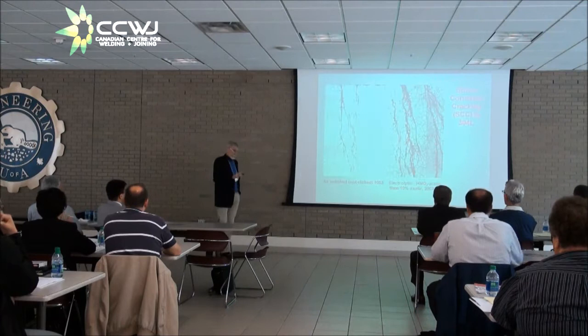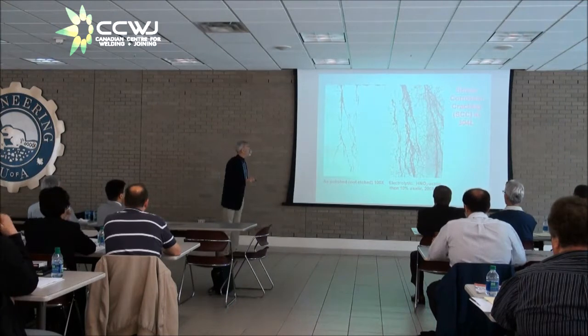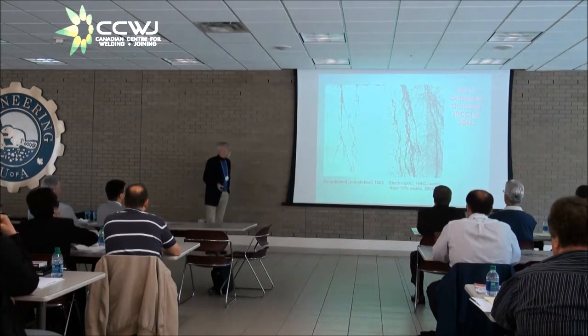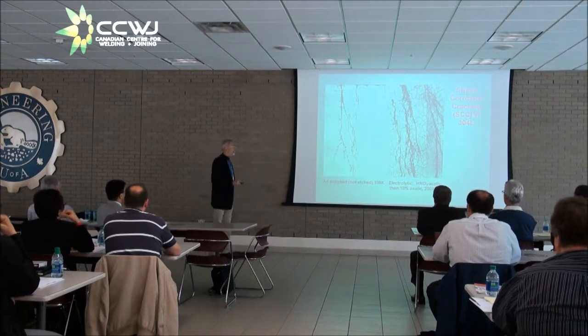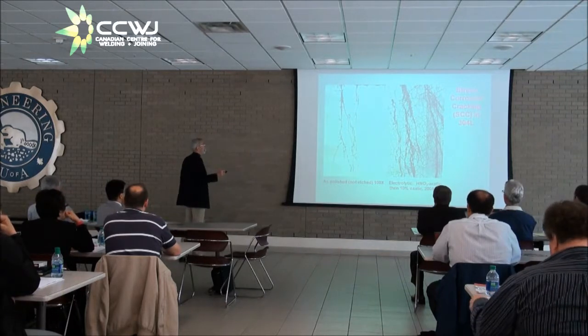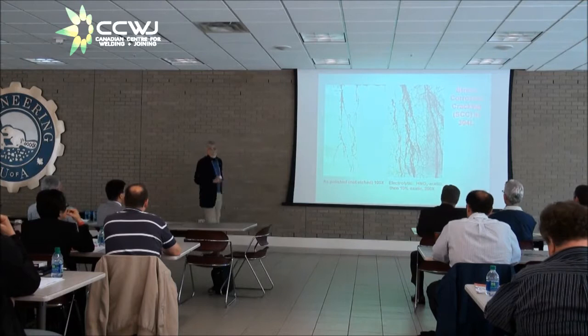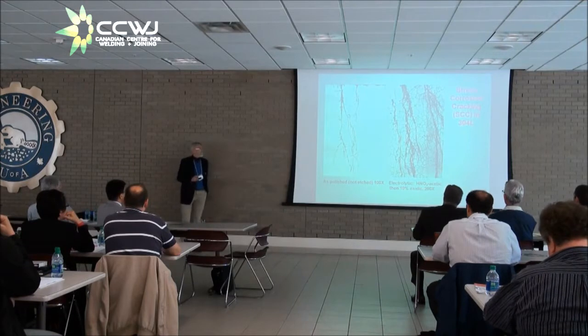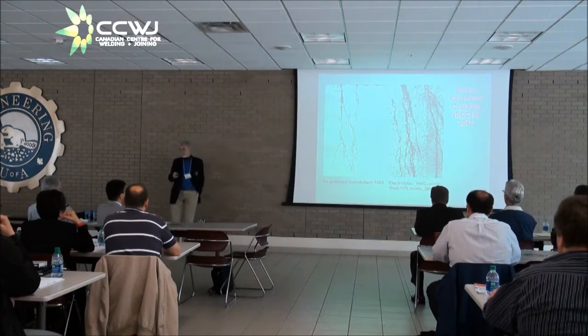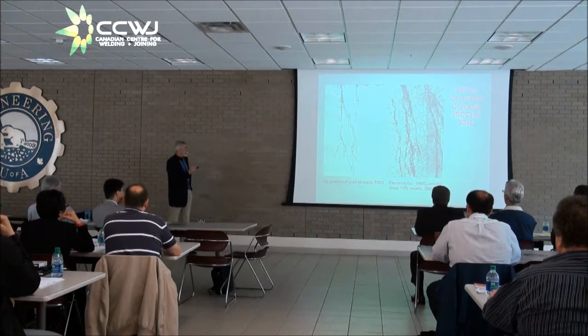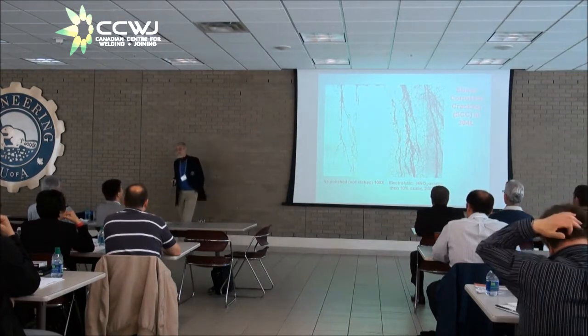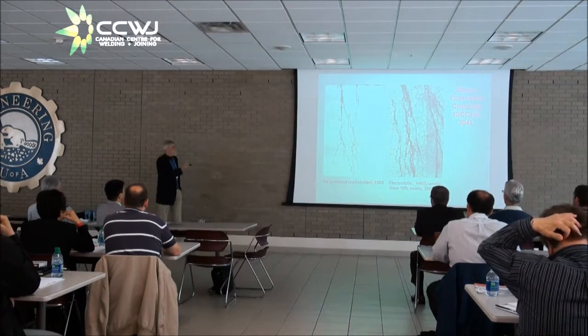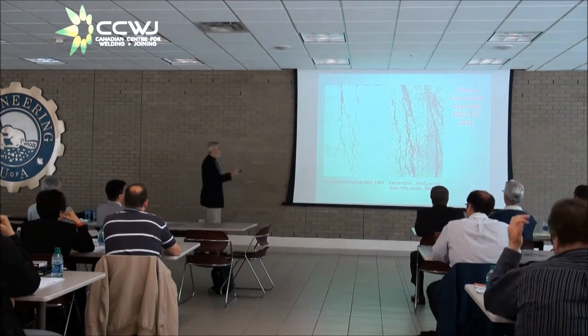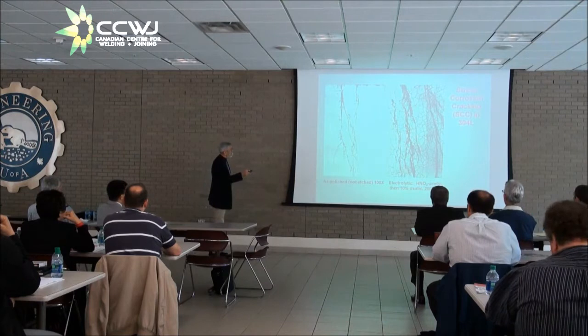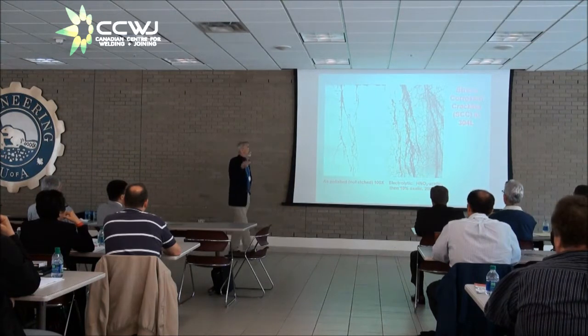This is a picture of a chloride stress corrosion crack, or a whole lot of chloride stress corrosion cracks. This is in 304 stainless, 304L. On the left side, you see the unetched appearance, and the signature of chloride stress corrosion cracking is crack branching. So you have a crack at the surface that becomes a multitude of cracks subsurface. And on the right-hand side, you have the same picture, but in this area here, enlarged, and the samples have been etched.